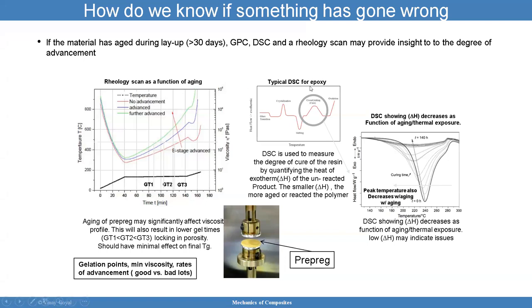A typical DSC for epoxy is going to look like this. You have a heat flow plotted against temperature. The DSC is then used to measure the degree of cure of the resin by quantifying the heat of exotherm of the unreacted product. A smaller delta H means I have a more aged or reacted polymer. So the lower the delta H, the more issues I have with the aging of that polymer.